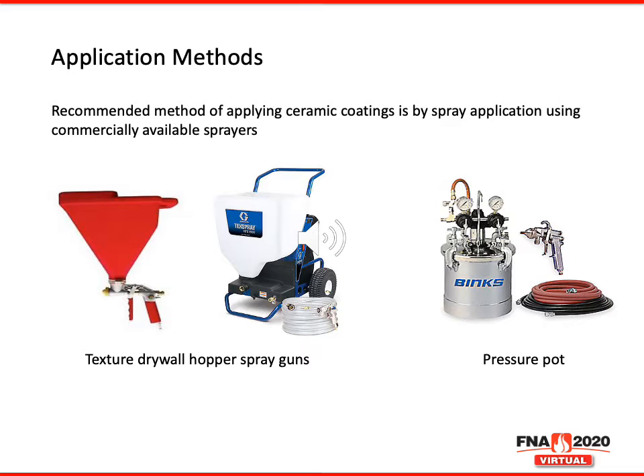Application methods and surface preparation are extremely important in the installation of ceramic coatings. Recommended methods of applying ceramic coatings are by spray application using one of the commercially available sprayers shown here. If the square foot area to be coated is relatively small, a typical paintbrush can be used to apply the coatings.